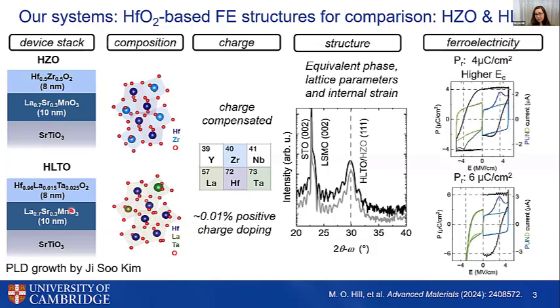And then finally, looking at the ferroelectricity, we do see a difference between these two films, despite them being quite similar. We get a remnant polarization of around 4 microcoulombs per centimeter squared for HZO, and then slightly higher for HLTO. So now we have two systems to compare that are structurally very similar, but have different ferroelectric behavior.